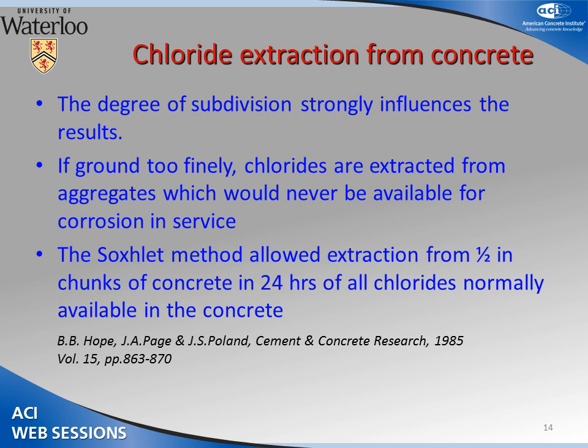As you'll hear from David Trejo later this afternoon, there has been considerable discussion among the different committees of ACI on how much chloride should be permitted in the ingredients, the components that go into concrete, to make sure that the steel in the concrete does not begin to corrode. Brian found out, what is obvious to everybody, that the more finely divided the particles, the more chloride is extracted. But this was the first measurement of that and the first quantitative evaluation.